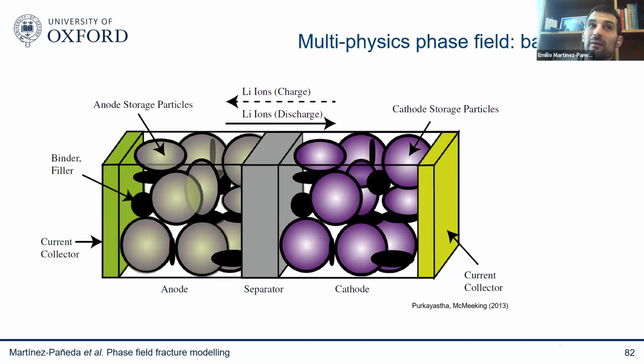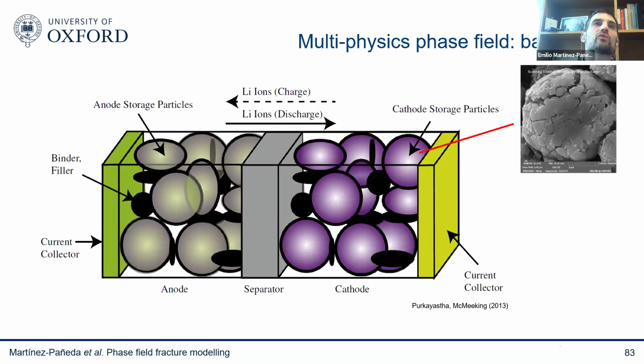And the problem is that every time you do this, you're basically swelling and shrinking these particles. You input a lot of lithium ions there, they change in shape, they swell and shrink. And when you swell and shrink those particles, you get cracks. And those cracks are the main reason why we need to change our phones or our laptops every couple of years, because we are full of cracks everywhere. So we decided, okay, can we do the same as before?